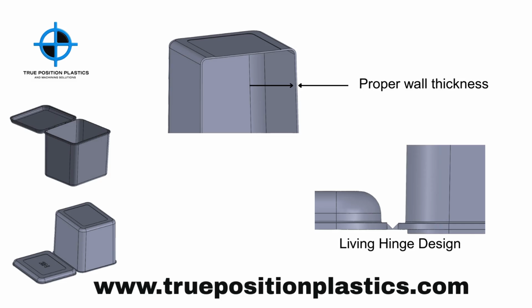So to mitigate this, standard design guidelines suggest coring out thick features, anything over about 0.150 inches. Always transition from thick to thin, never the other way around. That causes problems. It's also smart to place gates closer to the thicker regions to ensure they get packed out properly with plastic and prevent underfilling. And critically, avoid trapping heat in isolated spots, like don't put a big logo boss right on top of a thick solid dome feature. That's asking for trouble. True Position Plastics identifies these problem areas during DFM and often runs simulations to confirm material flow and cooling, making sure these issues are caught early, not after you've spent a fortune on the mold.